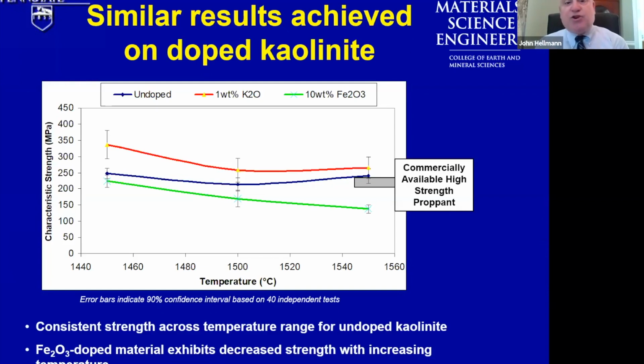Similar results were achieved in the doped kaolinites. We were able to sinter these at substantially lower temperatures, and we were also able to achieve the malted milk ball or core shell microstructures in these materials by exploiting the use of the iron oxide dopant. Well, we patented that work. That work was subsequently licensed. It's being exploited in the manufacturing of controlled specific gravity high strength proppants right now, which are being used around the world.